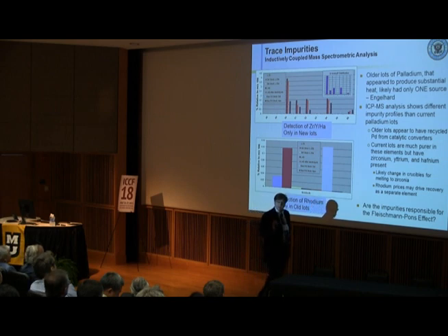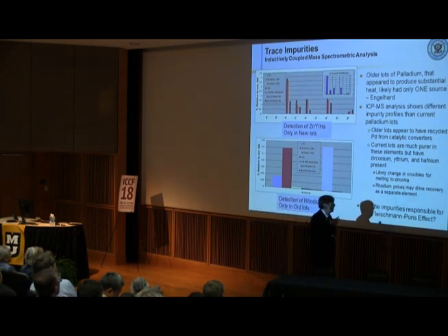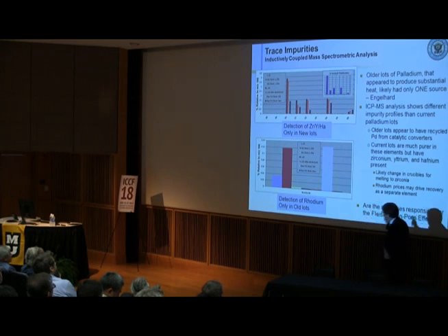They had zirconium in them, the rhodium was taken out, and hafnium was the other thing they had. That could be because the older lots of palladium were probably recycled catalytic converters, which have palladium, platinum, and rhodium in them. And at the time, the rhodium prices didn't allow one to extract it. Now they did. So they changed how they made them.